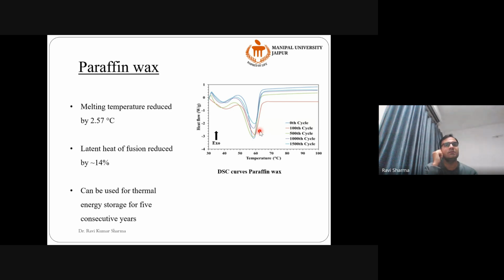So how do we see that? One cycle in a day - one melt and one freeze cycle in a day. If we have 365 days in a year, excluding rainy days and cloudy days, I roughly get 300 days in a year. So one cycle in a day, 300 cycles in a year, and then 300 multiplied by 5 for 5 years. After 5 years, this material will lose roughly 14% of its latent heat.